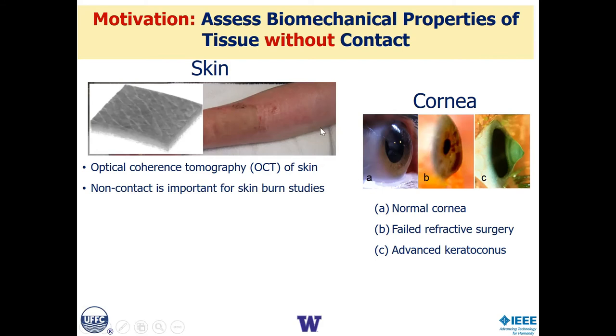But what's done right now is the matching of donor skin to recipient skin is done mostly by experience. The elastic properties of the skin are not tried to be matched in any way other than by experience. And we provide a quantitative tool which allows us to identify the appropriate skin to transplant and then monitors the transplant procedure and the recovery to ensure that the graft provides the elastic properties that are needed for a successful graft. And again, non-contact is important, especially for skin and reconstructive surgery patients.